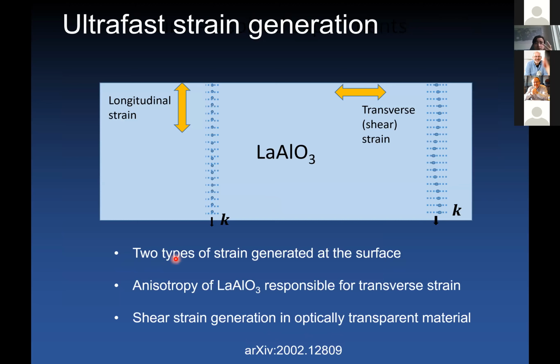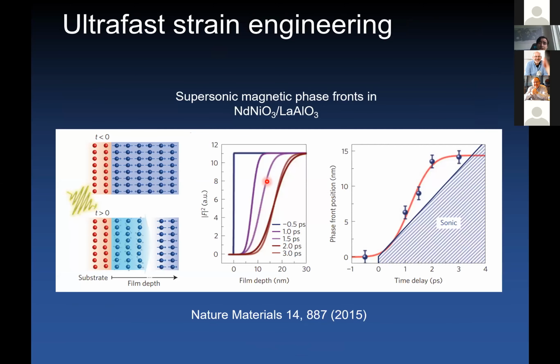Okay, so when you excite resonantly the lattice using strong laser pulses, then you have three phenomena. You have the generation of low energy modes of the Raman type, which involve coherent rotations of oxygen octahedra. And in addition, you have generation of strain waves that are propagating across your material. So what can you do with that?